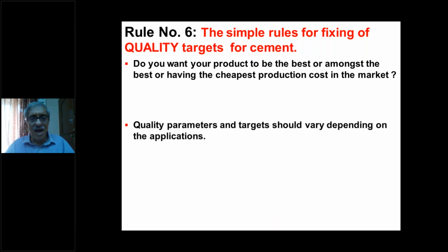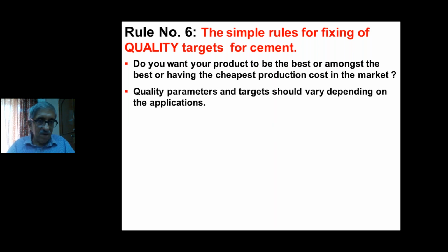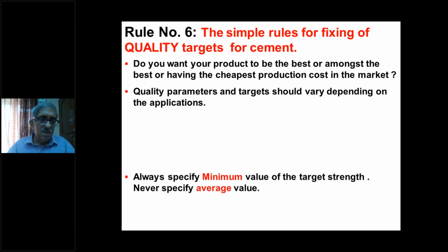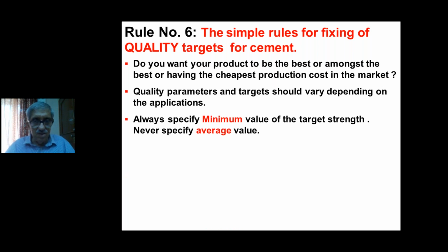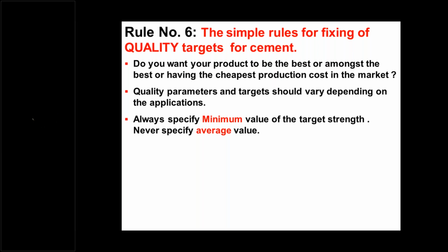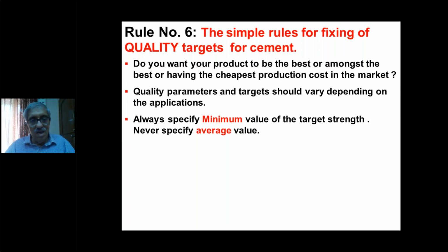Quality parameters and targets should vary depending on the application. Very important, because cement is used in several applications. Always specify the minimum value of the target strength, never specify an average value. If you say average value, it will mean that for the first 10 days you produce good cement and the next 10 or 20 days you produce bad cement, and the average will be okay. No, that is not the thing. Average is for an average person.